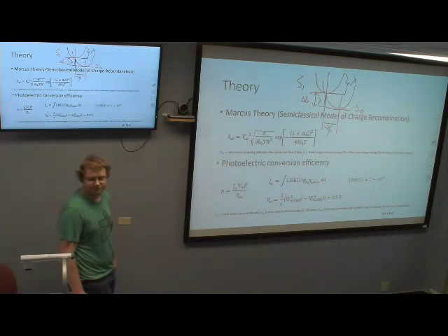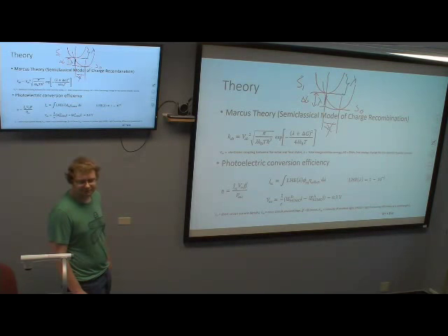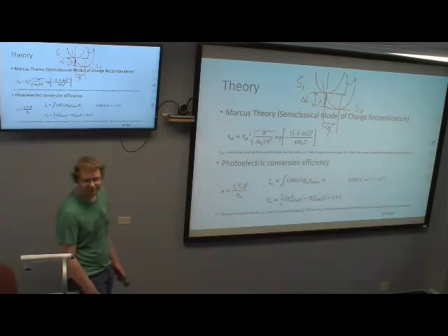Assuming parabolic behavior, you know the formula, k x squared, right? So having 3 points, am I right? 3 points or 2 points? 2 points is enough. You can do it with two because it's symmetric, right? The minima and somewhere nearby is enough to create a parabola, if you assume again that it's parabolic behavior. And then you can get this lambda and delta G just from your calculations.